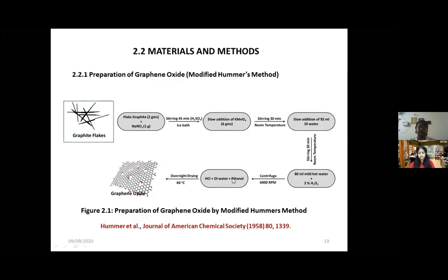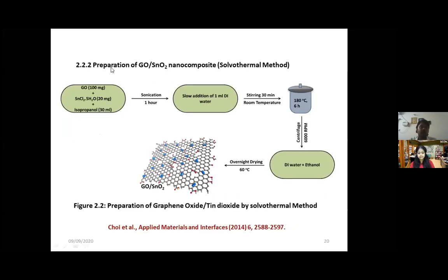After this centrifuging, the exfoliated graphene oxide sheets from the graphite flakes settle at the bottom, and unreacted metallic salts along with the solvents are at the top. So we filter it, and the settled graphene oxide sheet is dried overnight in vacuum at 60 degrees Celsius. This will be in the form of a black amorphous powder to the naked eye. And this is our first sensor material, the preparation of graphene oxide, tin dioxide nanocomposite.